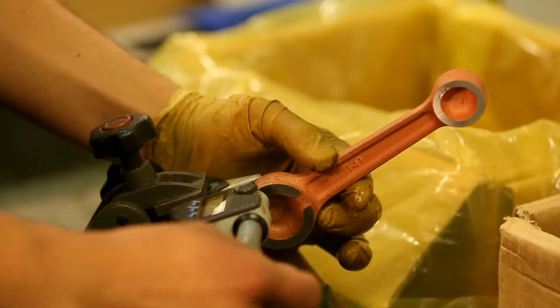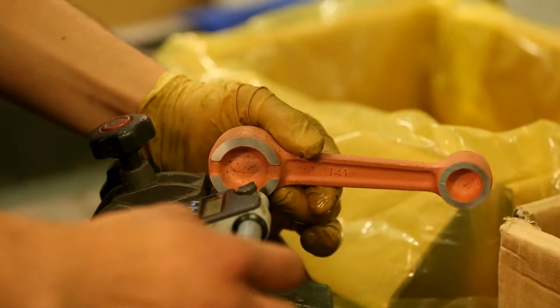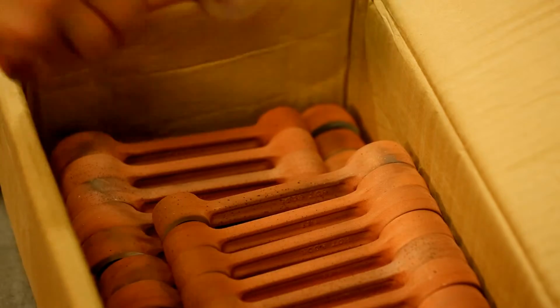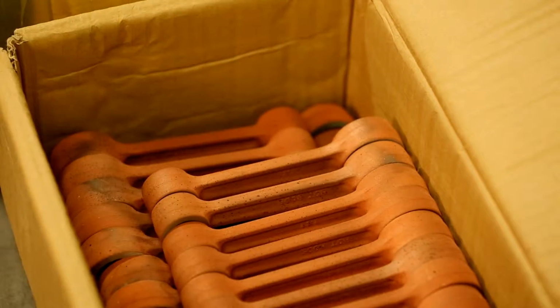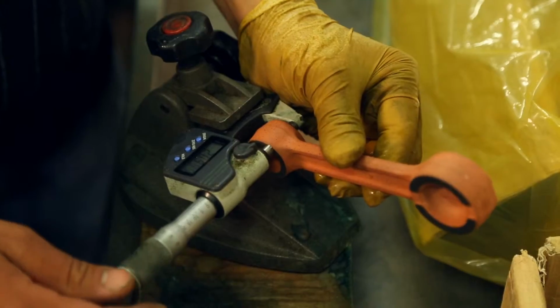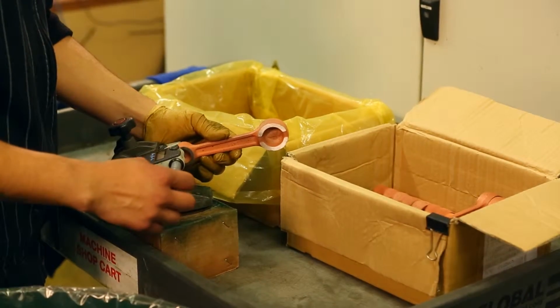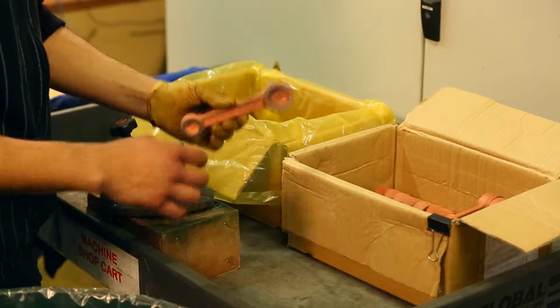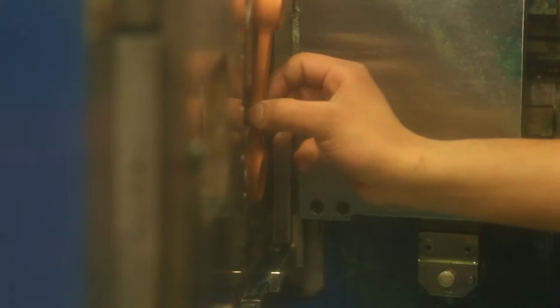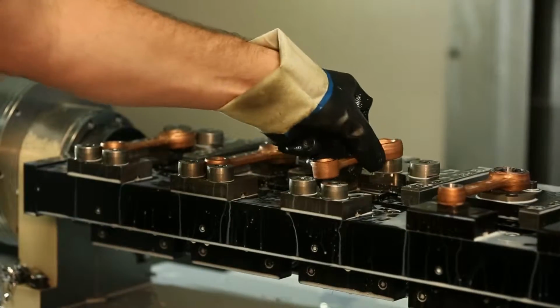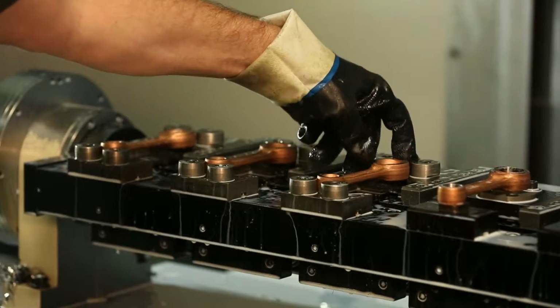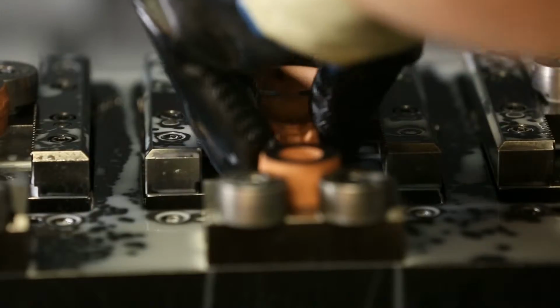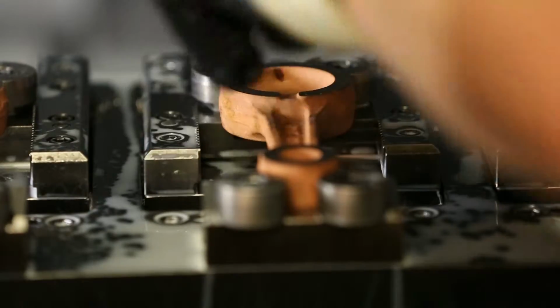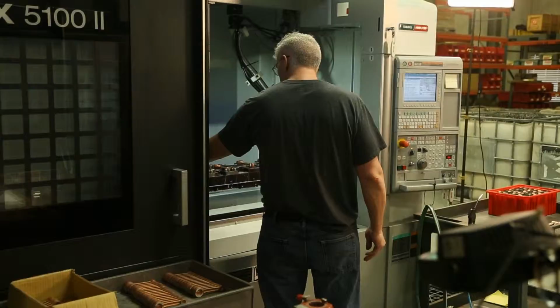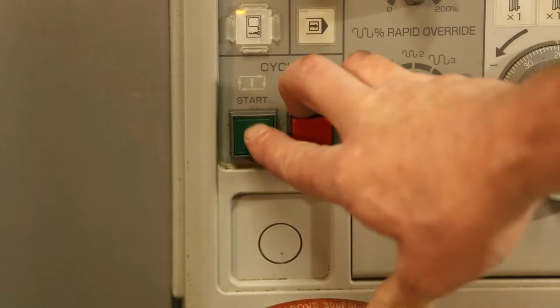The tolerance is held within 5 microns or 2/10,000th of an inch. This inspection of each rod ensures that any rod that may be out of tolerance is eliminated from going any further in the production process, thus saving time and money. After each rod is rough ground, they go into a vertical CNC mill for machining. The rods are then put in a CNC mill to machine all of the internal and external features of the rod. A special holding fixture is used so the mill can cut the internal dimensions and features of 3 rods and the external dimensions and features of 3 rods at the same time.